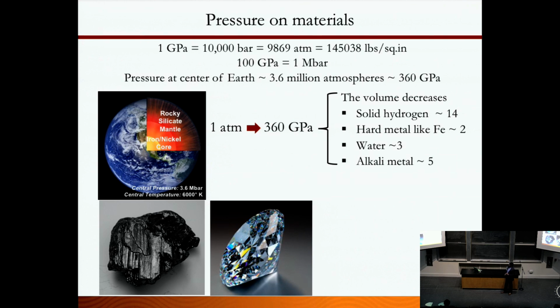And I'll give you another interesting example, which probably everyone in this audience knows about, carbon and graphite. Graphite is the most stable form of carbon at ambient conditions. But if you apply a little bit of pressure, it goes to diamond, and that's the most stable form of carbon at these conditions. So it is interesting to understand why graphite is stable at ambient conditions, why it's less stable at higher pressures and temperatures, and why diamond is very stable at higher pressures and temperatures.